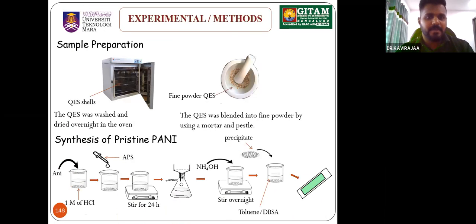For the experimental part, sample preparation, the shells were first washed and then dried. After that, we ground them, and then we also did some sieving. Then the synthesis of pristine PANI we carried out via the chemical oxidative method, where we used an oxidant, and we also used the dopant at the final stage so that it can become uniformly doped. We got a green color solution that we coated on a glass substrate. Next slide.